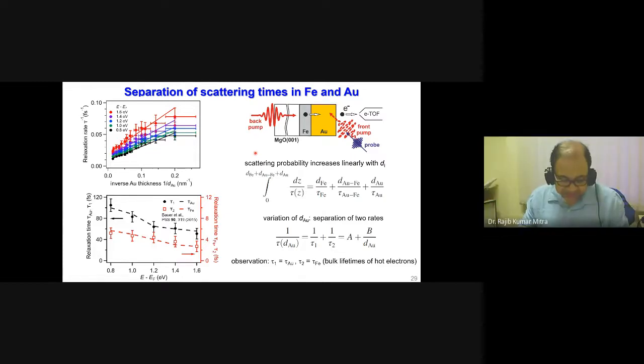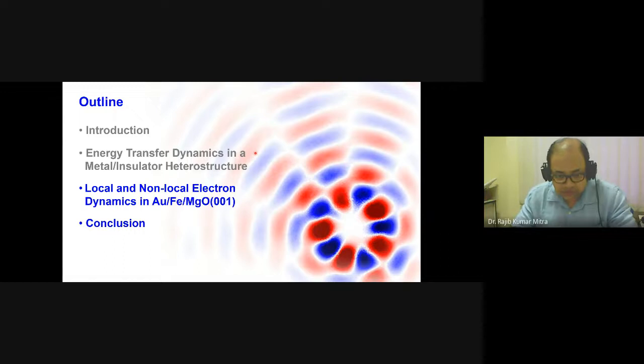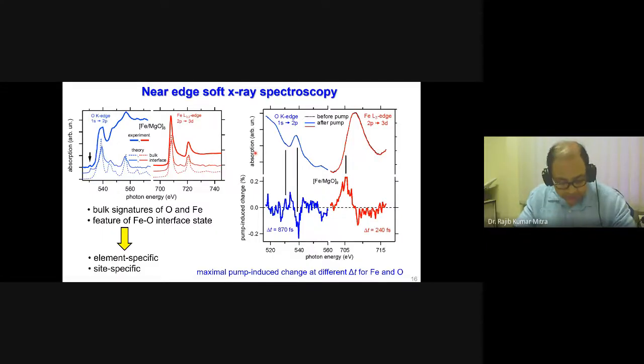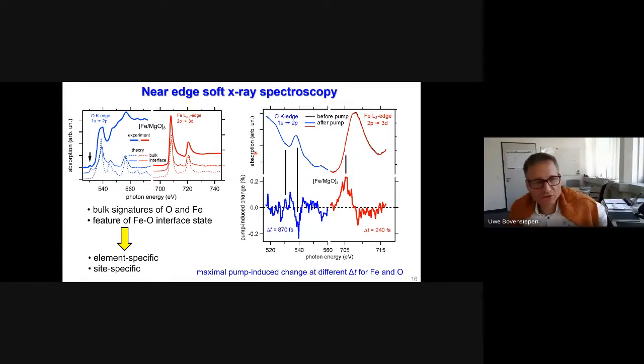Very interesting, Professor Bovensiepen. Regarding the UV pump and X-ray probe experiment, you can identify the bulk contribution and the interface contribution separately. I just missed how you can separate the bulk and interface contributions with UV pump and X-ray probe. And my question extends to this: if you pump with, say, a small gap, like with a terahertz pump, then what will happen to small transitions?